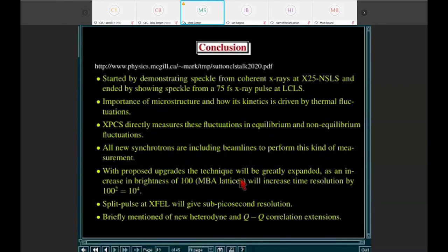I guess one of the things, I'm looking at my notes, that I meant to mention earlier, I did mention it indirectly, is that the first time we made our beam coherent, even without a sample, we saw a speckle pattern. It turned out to be related to the microstructure of the beryllium windows. It actually was the boron nitride spray on the beryllium windows that was used in order to keep the beryllium windows from oxidizing in these intense X-ray beams. So don't underestimate the amount of impact that will happen, because basically the coherence on the optics will lead to speckle patterns unless the optics is of exceptional quality.